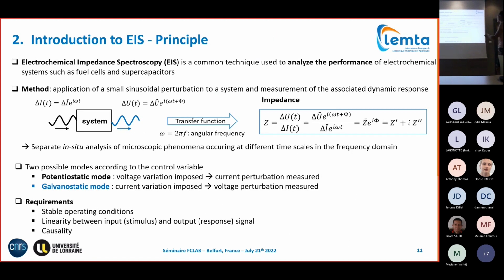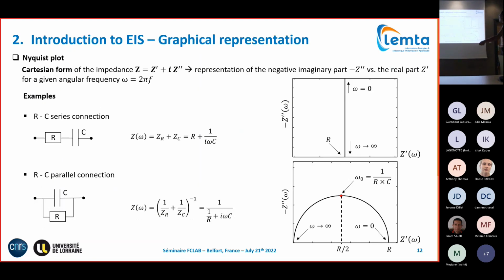Okay, the impedance is a complex number that you can represent in two different modes. One in terms of the amplitude and the phase shift between the stimulus and the response, and this would be the Bode plot, which you do not have, so I won't show you here. Or you can choose a Cartesian representation, meaning you represent the negative imaginary part versus the real part for the frequency, which is shown here, called the Nyquist plot. It's more convenient for direct analysis, so that's what we primarily use for our analysis. That's what I will use here in the presentation.